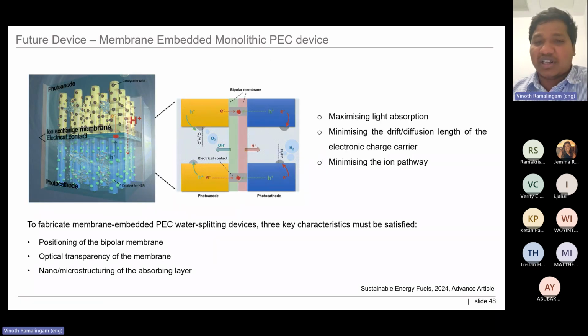So based on the recent literature, what we found is the future device would be a membrane-embedded monolithic PEC device. In addition to the issues we have seen so far, there are other problems in the case of ion diffusion between the electrodes. In that case, putting a membrane between the electrodes can help us transfer the ions quickly, which can improve the overall performance. In addition to that, they are proposing a device that can maximize the light absorption of both photoanode and photocathode, so that you can improve the overall performance.